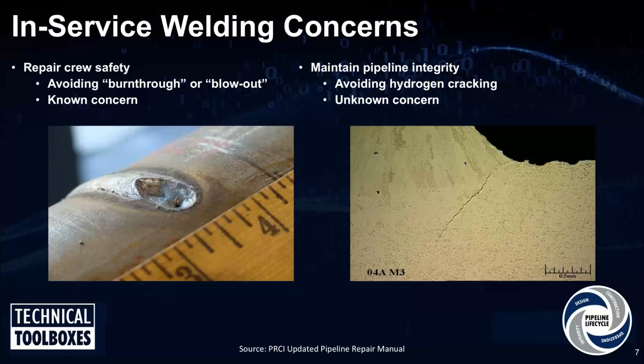But of these two concerns, in my opinion, I think hydrogen cracking tends to be a little more of a concern. And the reason I think it's a little more of a concern is that it's an unknown risk, right? So you might have a risk of cracking, but if you have a crack, you might not know that you have a crack.